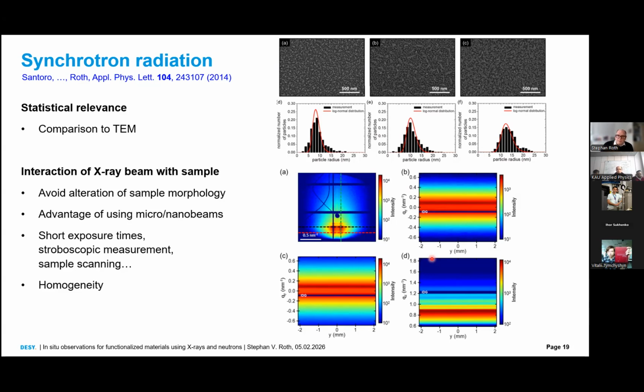In order to avoid this, we take a series of these images with very short exposure, 0.05 seconds or even smaller, and we look at them as a function of time. If there is no change in the images, this means the X-ray doesn't induce beam damage. As soon as you induce beam damage, you see a broadening here. You don't see it in the wide angle scattering pattern; it is already too late when you see it there. You see a slight broadening when you have radiation damage. This is then the case where we say we cannot measure more than 0.5 seconds per point, and we typically measure only 0.1 or 0.2 seconds per point.